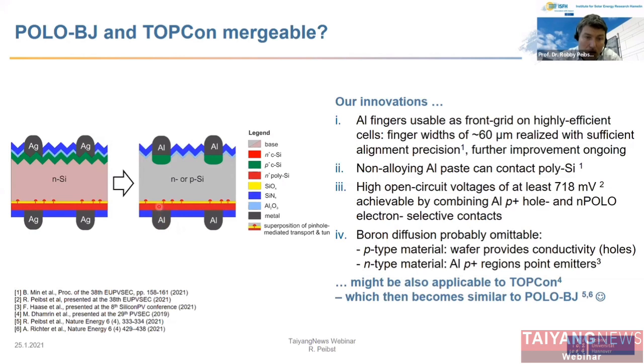And as we've shown, the aluminum-alloyed p+ regions here on the front side, in combination with the n+ polysilicon on the rear side, are capable of high VOC values. So there's no large efficiency limitation. And we have also shown that you can omit the boron diffusion and utilize either the conductivity of the p-type wafer for hole conduction to the contacts, or use these p+ regions here as local point emitters.